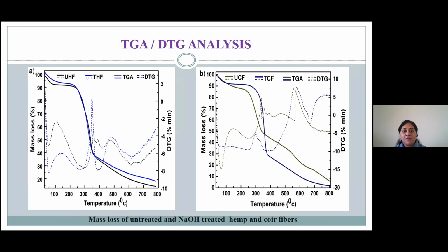We come to the thermogravimetric analysis and the derivative thermogravimetric curve. The first major loss happened at around 110 degrees Celsius and also at around 300 degrees Celsius, from the peaks of the TGA curves.